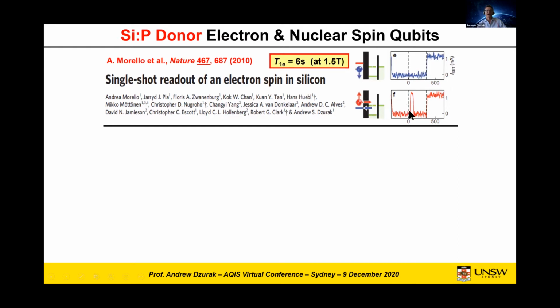A short time after that, just a couple of microseconds, depending on the tunnel rate, a spin down electron from that transistor will tunnel back onto the island, and after that, further current in the SET is blocked, because now this electron, which is spin down on the atom, can no longer energetically tunnel into the transistor. And so once the electron is tunneled off, the current is turned off. So what this provides is a very high fidelity fingerprint of the state of the spin on a single atom. And this was an incredibly important enabling result. It also showed in this experiment that the spin lifetime of the electron on this single phosphorus atom was many seconds, so effectively incredibly long compared to any of the operation times that were required for qubit control and readout.